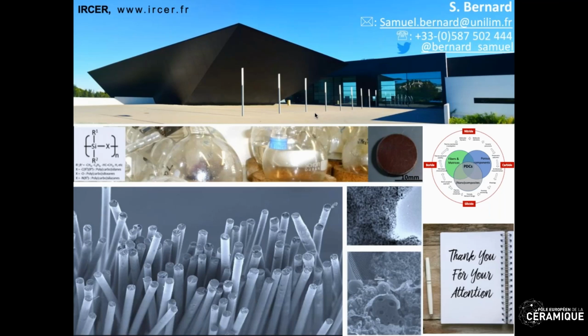Okay, we have 2 other questions. Do you have examples of application of PDCs as thin layers? Yeah, a lot. We have a lot of examples. In fact, controlling the thickness is not a problem. You can form very thick coatings and use them for antibacterial applications. Or you can also really control the thickness. But as I mentioned previously, again, the issue is the volume shrinkage. You should control this volume shrinkage. If not, you can crack your coating, you can produce defects. So the main issue is the volume shrinkage. And usually to produce coatings, you mix with fillers.